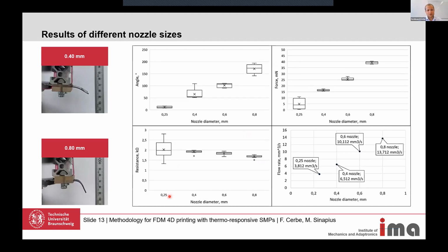So to not lead you with only the methodology into this Friday evening, I will also show you some new results that we acquired. We changed the nozzle sizes from 0.25 to 0.8 millimeters. And here on the side, you can see the transformation of the 0.4 millimeter nozzle and the one from the 0.8 millimeter nozzle. You can see that the performance of the 0.8 millimeter nozzle is better than the 0.4 millimeter nozzle. Furthermore, the force also increases, which is expected, because when we have a larger deformation and we block this deformation at the printed state, then we expect a larger force.